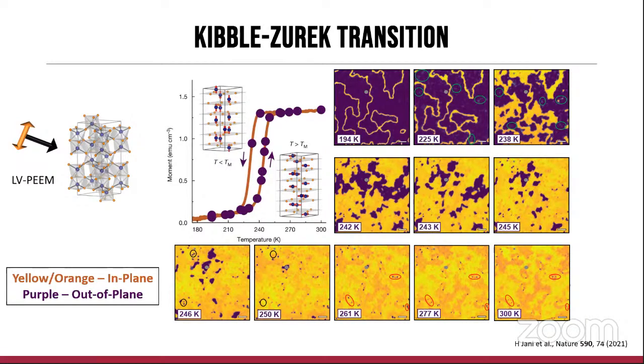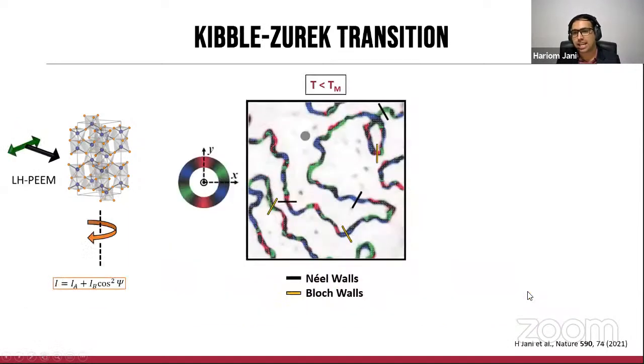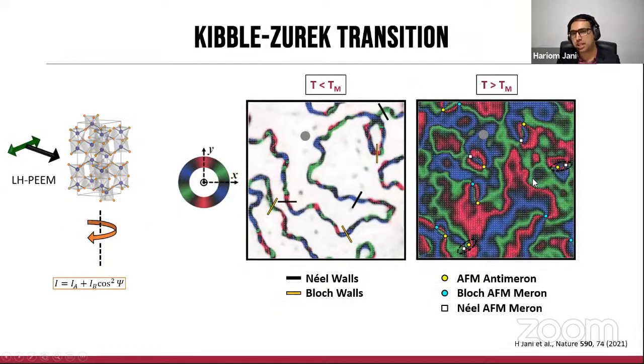But we have done much more exhaustive mathematical analysis also to convince what are the various permutation combinations in the system, and all of that can be very clearly distinguished with the polarization. But of course, if you want to really resolve the orientation of the in-plane textures, the way to do that is by using the vector mapping technique, which I've mentioned before, which then actually reveals there's a rich mosaic of structures. Okay, thank you.